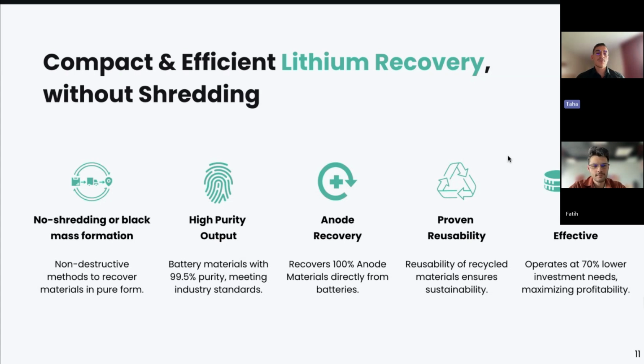But looking into the results that we have, summarizing everything: we do not shred or create black mass formation. All we do is non-destructive methods to recover the materials in the pure form, which is leading to a high purity output, which is pretty important in order to also gain profitability from an economical perspective. Because while black mass is currently treated at around $4,000 to $5,000 per ton, we have the active materials and the purity levels that can be sold for 5 times the price of the black mass.